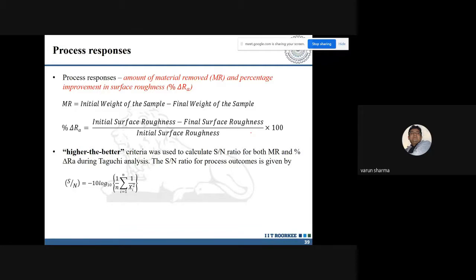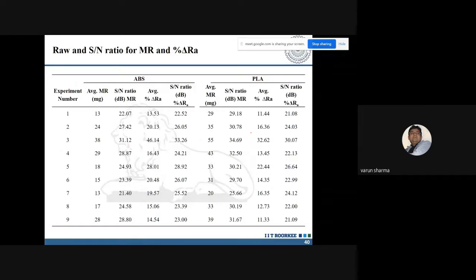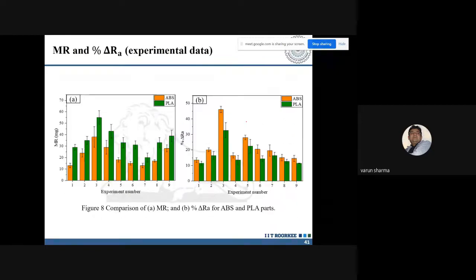So for the Taguchi, we went for a higher-is-better kind of approach, and these were the characterizations for the different sets of work materials, that is, for the ABS as well as for the PLA. What you could see from here is that, as compared to the ABS, the average material removal was higher for the same set of experimentation for the PLA, because it was relatively softer in nature. Now, however, there was a contradictory experience over here, and that contradiction came up in the average surface roughness, which was higher in the case of ABS and lower for a similar set of parameters in the case of PLA. So what is happening in the process?